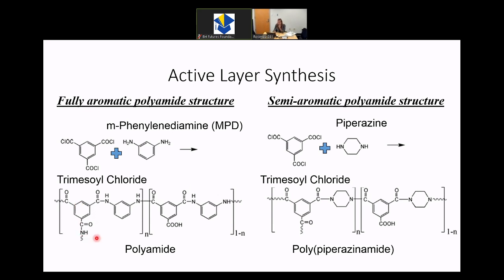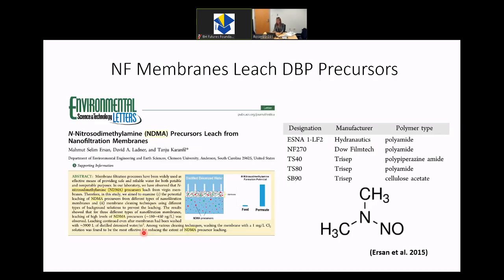And for the nanofiltration membranes, those can be either semi-aromatic or fully aromatic. So in a recent study, there was evidence that there's some kind of precursor leaching from nanofiltration membranes. This study looked at 5 various types of nanofiltration membranes, and they measured using something called formation potential. They measured what is leaching from these compounds.